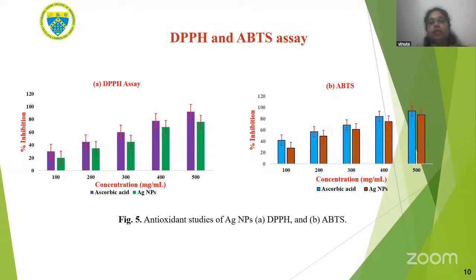So further, the synthesized nanoparticles' antioxidant properties were determined by using various assays. Antioxidant properties are important. So the antioxidant properties were evaluated with the DPPH, ABTS, FRAP, and FICA assays. Here, DPPH and ABTS assays are there. Different concentrations, that is 100 to 500 microgram per ml of the synthesized nanoparticles, were used. This color is for the ascorbic acid and this green color for the synthesized silver nanoparticle. Ascorbic acid is used as a standard drug, as a regular medication.